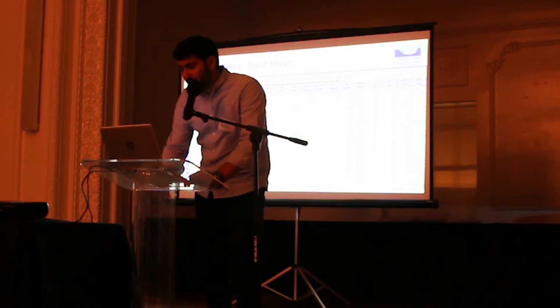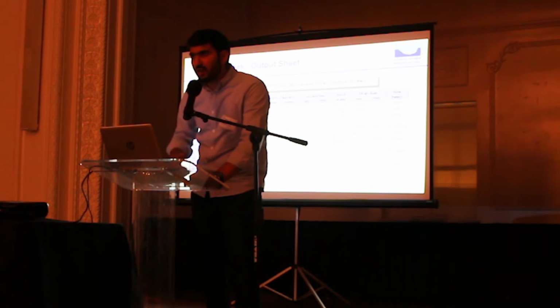From these cases, I will try to examine the flow pattern estimation, or the flow pattern calculation here. For the three cases, I have low gas flow rate, medium gas flow rate, and high gas flow rate. And again, from the output screen, for the three cases, since I have low temperature, low pH, non-scale was predicted, and I also have the corrosion rate value listed here.